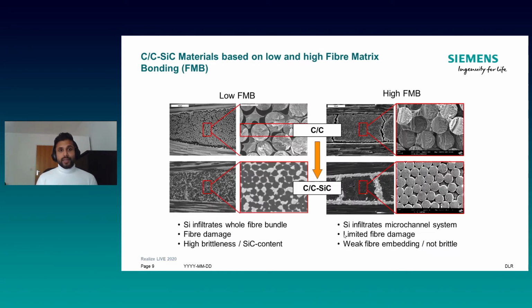Just to give you another insight into the next step, for example, if you have low fiber matrix bonding, what happens is during the siliconization step, the molten silicon flows or reacts not only with the carbon matrix, but also with the carbon fiber. And this means in the end, we end up with a fiber composite, but the property itself will not be as good as any fiber composite, because this particular material, where even the fibers are siliconized or damaged by silicon, will be very brittle in nature and as brittle as a monolithic ceramic.